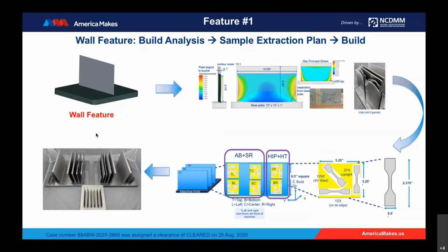So the first thing that we did was to understand the stress states that the wall would see if we make a wall of this size. We understood that there could be effects of warpages, there could be an effect of high stress locations leading to cracks. So that's what we did some simulations on. And then we went forward in terms of extraction strategies, exactly where in the wall we are plucking the samples out of, what is the orientation with respect to your build axis, etc. And then once we had a clear identification of these schemes, we finally went through the build execution, what you can see in the bottom left, different walls with different thicknesses being built in this DOE. So we go to the next slide.